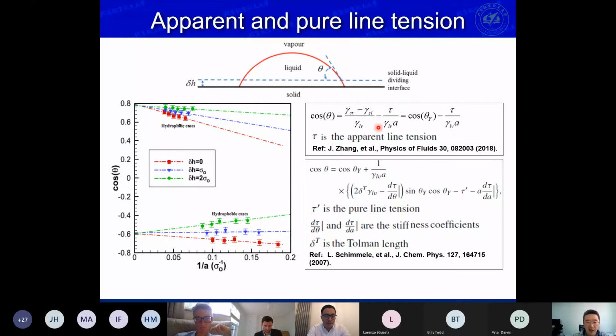On the other hand, if you only focus on the contact angle at the macroscopic scale, the pure line tension is not so important. You can just measure the contact angle at the nanoscale, and then you can do linear fitting and extrapolate it to the macro scale, and you can get the same macroscopic contact angle. It's fine. So this is the first part about the static wetting and how the line tension affects the contact angle.